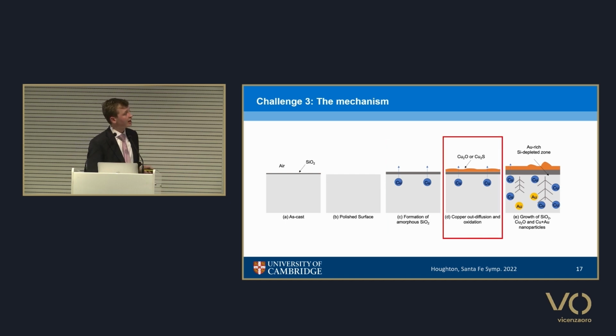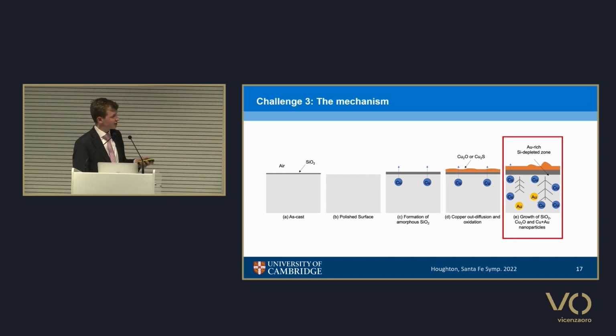And ultimately, that leads to these rather, well, they're not dendrites, but because they're not crystalline, we use the term dense branching morphology. But in essence, we have this inward oxidation of silicon and the outward depletion of copper, which leads to this reddish-brown appearance on the surface.